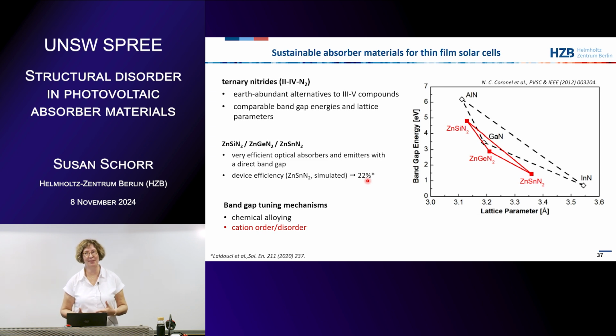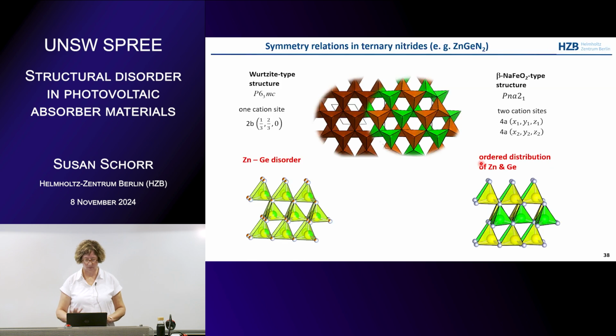But what was most interesting for us with these materials is that you can not only tune the band gap by alloying, what you normally do, but you can also tune the band gap by cation order or disorder in the material. And that's why we studied zinc germanium nitride, to have a look if we can change the band gap by changing the cation disorder. Now, what does cation disorder mean in these materials? Zinc germanium nitride, as the other two nitrides, has 2 possible structures to crystallize in. One is the Wurtzite type structure, where you have only one cation site, the 2b site. So both cations are on that site, and of course then you have disorder. If you have only one site, no chance to get order.